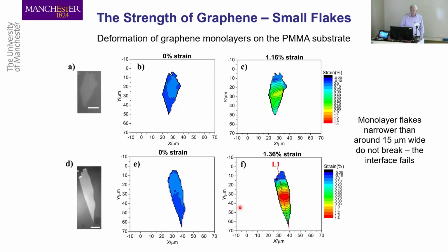We tried it on smaller flake. This was a smaller flake, only about 10 or 20 microns wide. This one, we couldn't break it. This one slipped. The interface failed before it would break.